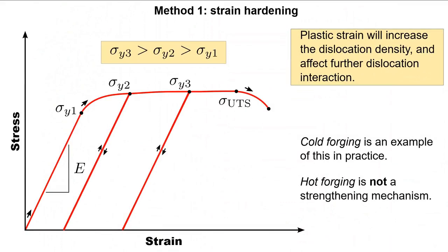In an early lecture, I described a uniaxial tensile test whereby multiple loadings were applied. I showed 3 different loadings of the same specimen, whereby the subsequent point where it yielded was the stress level which was last attained in the loading prior. This is a clear example of strain hardening, whereby it is more resistant to deformation based on prior plastic loading. You can see that the yield stress attained in the final loading event exceeds the first by a fair margin.